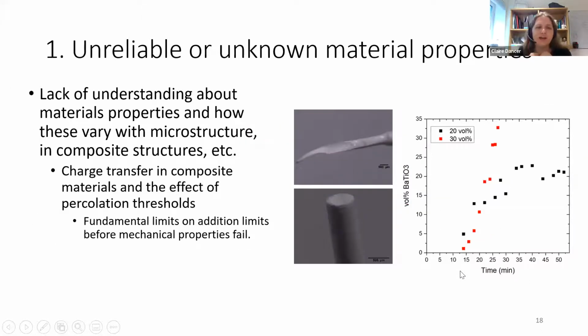And that can also have an impact in a related sort of area, which is that we see difficulties encountered because we reach a maximum value at which we can add things. Sometimes that's due to all the additions in the material joining up together in this thing called percolation, where you form a connected network of all the particles and they're all sitting next to each other. And that changes the properties of the material. Sometimes it's just because you have all sorts of interactions between the materials, and they can't actually mix enough to be able to interact in that way.